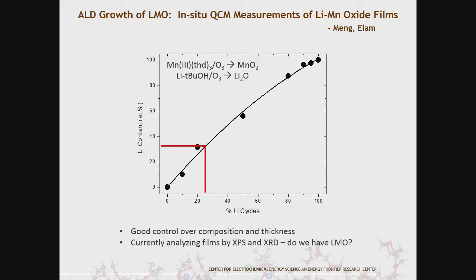This is other work from Jeff Elam's group. They're doing ALD growth of these materials, using manganese 3 precursors alternating with ozone, and then this lithium precursor with ozone. By changing the relative fraction of these cycles, they can control the lithium content. So this red line corresponds to what should be LMO.